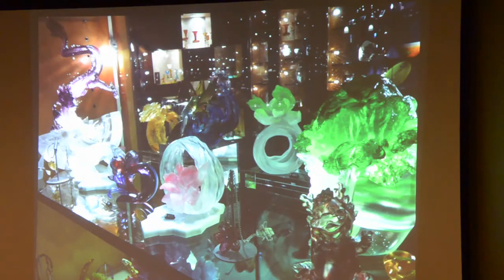There are other tricks that we can deal with to get some glossy surface, but there are compromises there too, because that dragon is not going to have glossy surface in the crevices. It's not as nice. If you were to do that with blown glass, everything will be a beautifully smooth surface because it's all globular, organic smooth surface anyway, because it's liquid surface tension that you're working with. But for cast glass, you can fire polish it after you've demolded it and maybe sandblasted it, slowly heat it back up to temperature, take an oxyacetylene torch and just blast that surface really fast, and it will smooth it off. You can lose detail when you do that, but it'll be really nice and smooth.